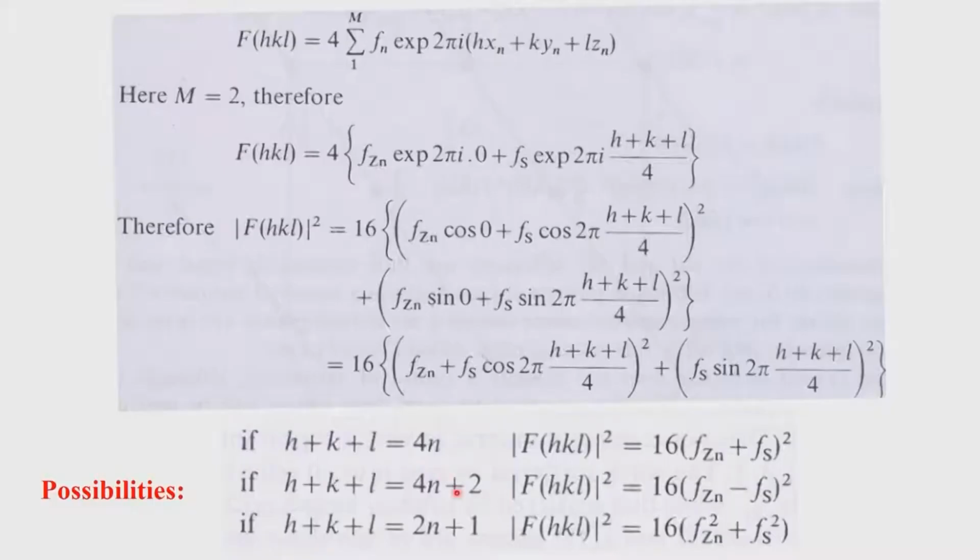Whenever we have translational symmetries associated with the space groups, we will get special positions. We do not get special positions, for example, in case of P1, but we get special positions in P1 bar, because XYZ and X bar, Y bar, Z bar can give rise to several centers of symmetry positions which are independent of each other. And therefore, if the atoms sit there, they are very special. In other words, they will give Z equals 1 rather than Z equals 2, and that gets reflected in terms of the systematic absences we see.